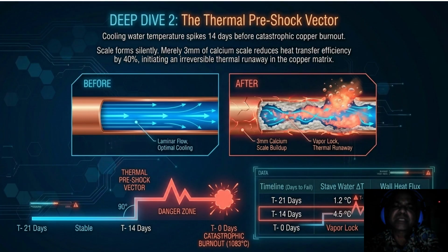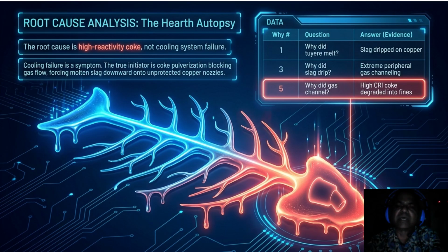So when that explosion happens, when the stave finally melts, we have to perform a hearth autopsy to find the real culprit. And this slide is about a root cause analysis, the details of the hearth autopsy. So when a stave fails, most people point at the cooling water, but look at this hearth autopsy fishbone diagram. The descent from the blue symptom into the neon coral root cause. Why did the stave melt? Because the slag dripped onto the copper.